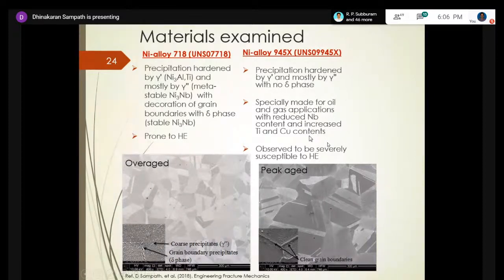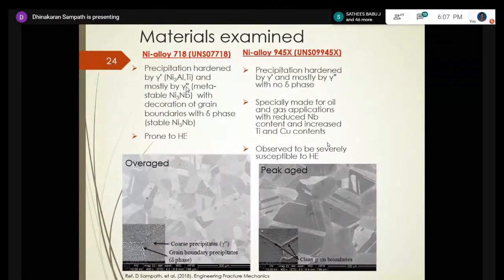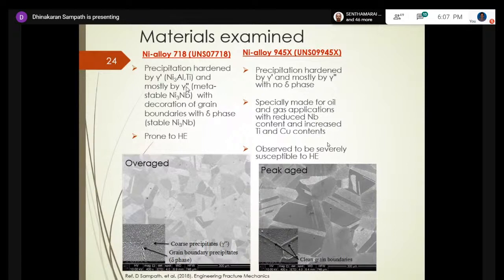Before that, what is precipitation hardening? That is a strengthening mechanism, whereby they rely on fine precipitates like gamma prime and gamma double prime. The moving dislocations cause the plasticity, but these precipitates stop them. When they are stopping, the amount of load required to cut the precipitate or just form a loop, they call Orowan looping, means we need to apply more stress, more load, to get away from the precipitate. Thereby it increases the strength of the material.